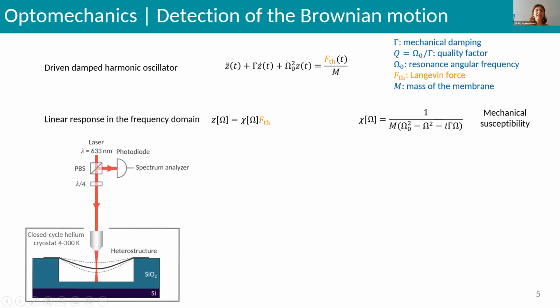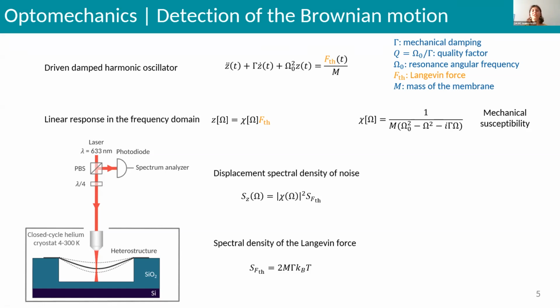So for this, we use an interferometric detection. So we focus the laser on the heterostructure. So the light will be reflected not only by the membrane, but also by the substrate, forming a Fabry-Perot cavity. And the length of this cavity will be modified by the motion of the membrane. So the motion of the membrane will be encoded in the reflected light and sent to a photodiode and then to a spectrum analyzer. So the spectrum analyzer will measure the displacement spectral density of noise, which is proportional to the spectral density of the Langevin force.